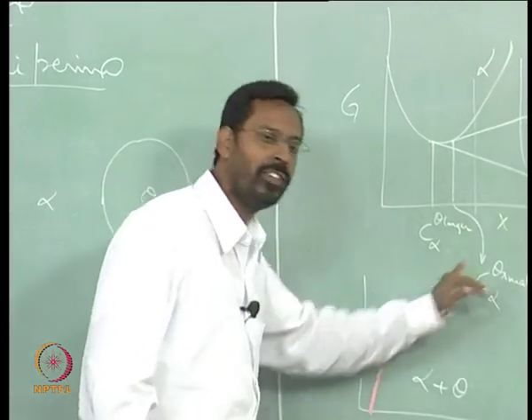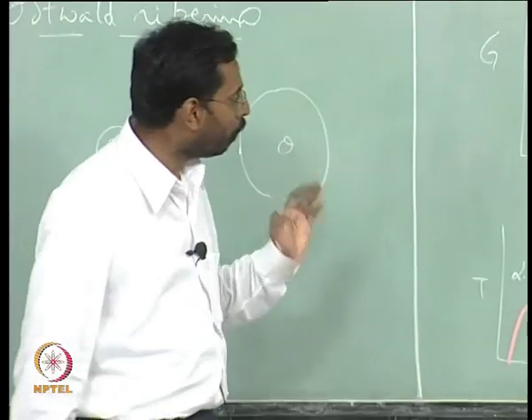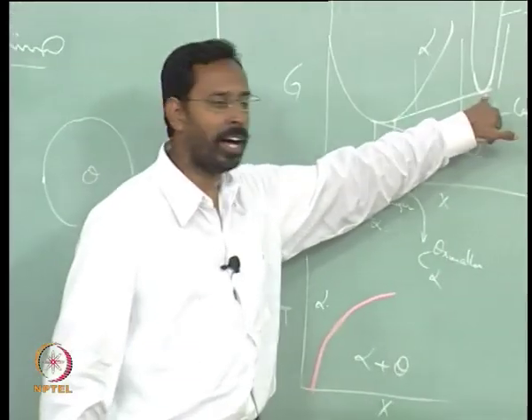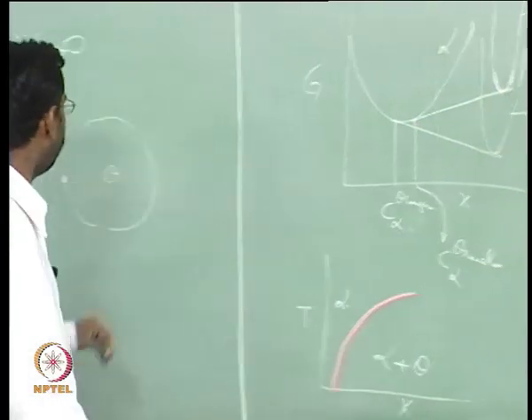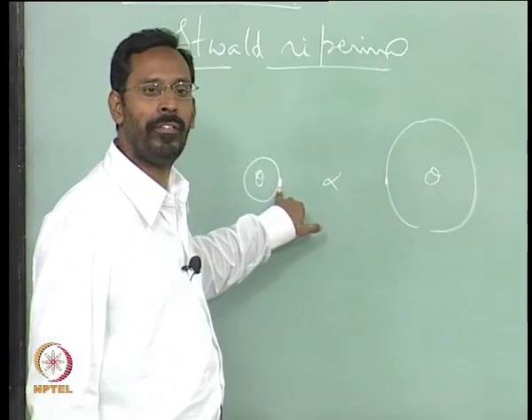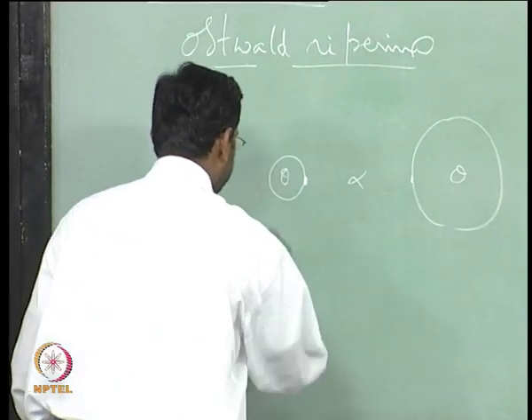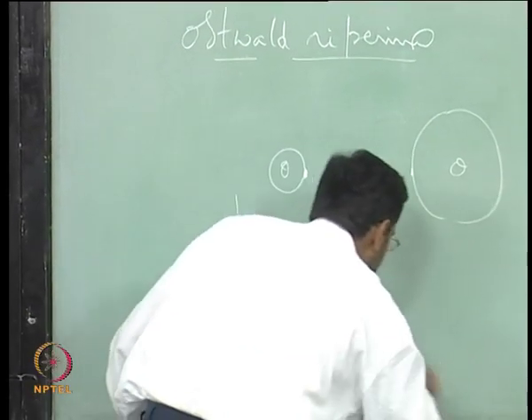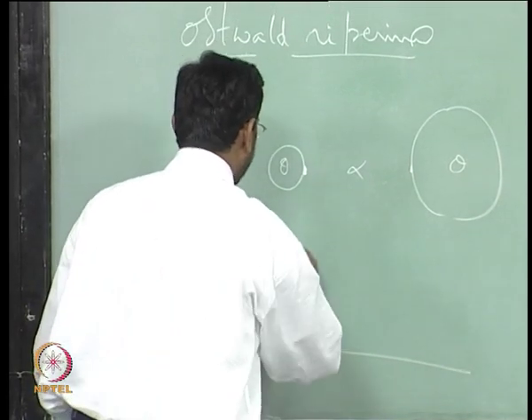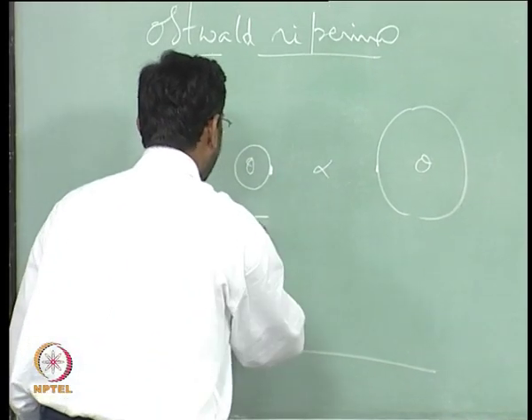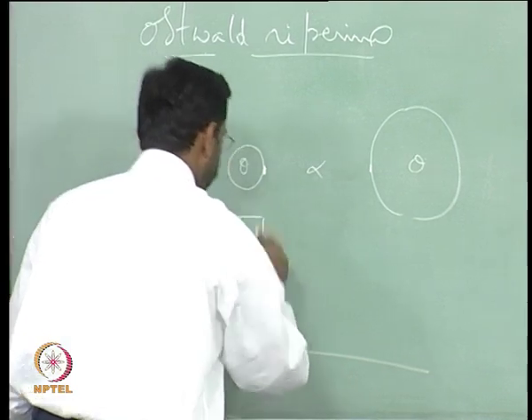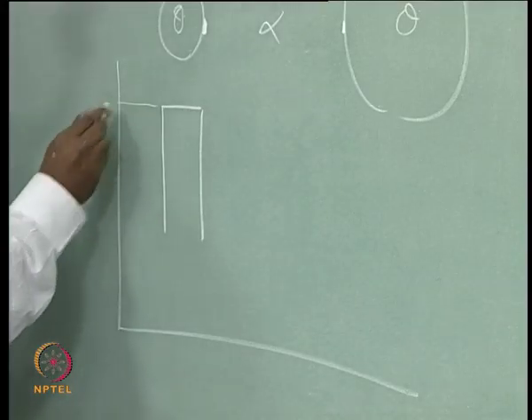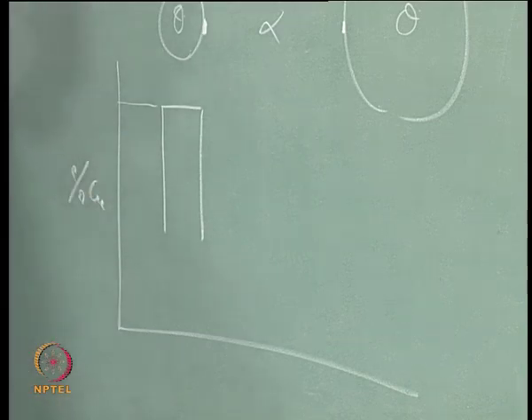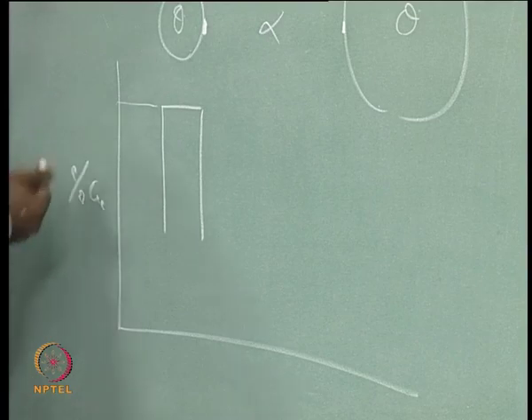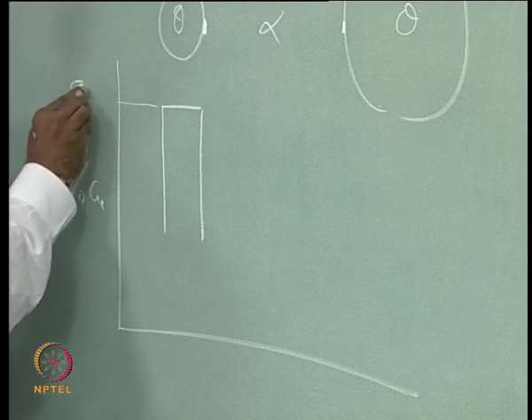So, this solvus is in principle for an infinite size, and the moment I assume that the theta has a smaller particle size, you would see that the composition will be different. If I try to draw, let us imagine that this precipitate has a certain composition. This is the composition in terms of percentage copper. If I plot, this is some value, whatever the Al2Cu composition is. In terms of weight percent, it is approximately let us say 55%.